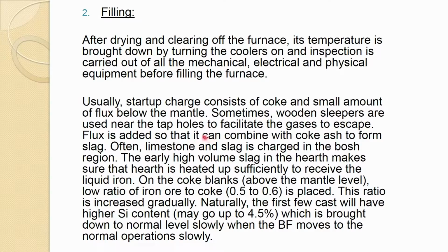Flux is added as mentioned here, so that it can combine with the coke ash to form slag. Often limestone and slag is charged in the Bosh region. So, the early high volume slag in the hearth makes sure that the hearth is heated up sufficiently to receive the liquid iron. So, naturally you are putting a small amount of flux. So, starting slag is more towards the siliceous side, silicon side, and that is actually good, and you also need high volume slag. So, you put more slag and that makes the hearth heated up. So, it is able to collect the liquid iron when the furnace is in normal operation.